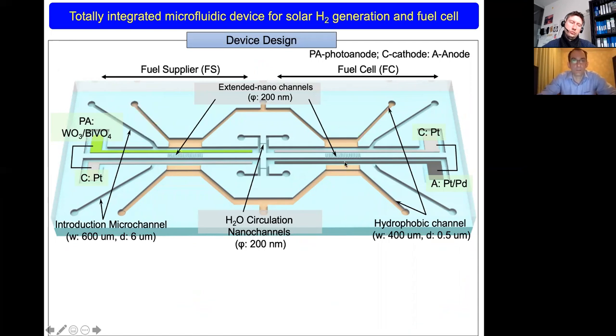and the fuel cell. So what we have inside is the integrated tungsten oxide bismuth vanadate material in the microchannel. Here is the platinum counter electrode integrated. And these two microchannels are connected by an extended nanochannel. So this is for the proton transport. And here we have the shell of the microchannel, which is modified by fluoropolymer. This is for the gas separation, because water could not come here due to the huge Laplace pressure. If you see here the dimensions of this introduction microchannel and hydrophobic microchannel, they are really tiny, in the micrometer range.